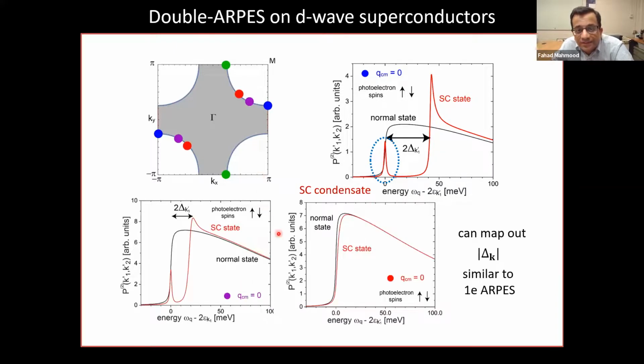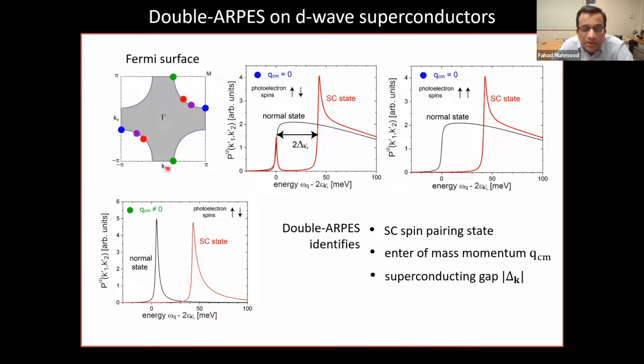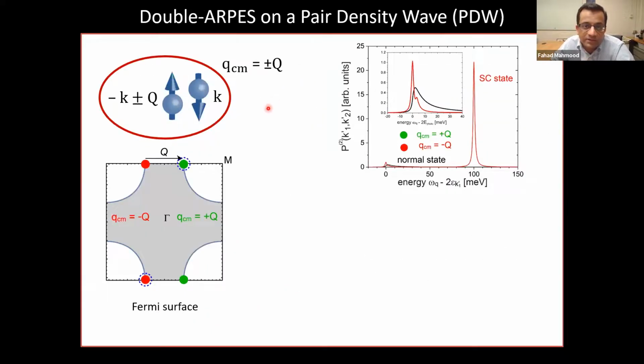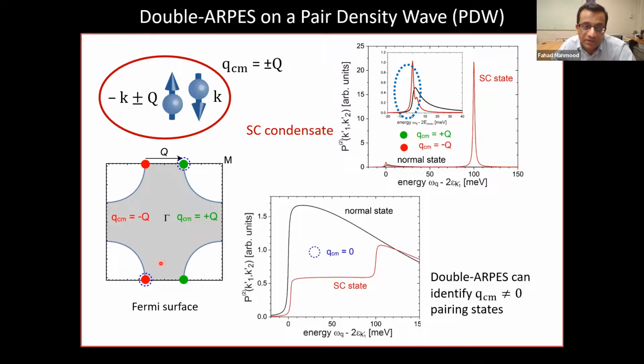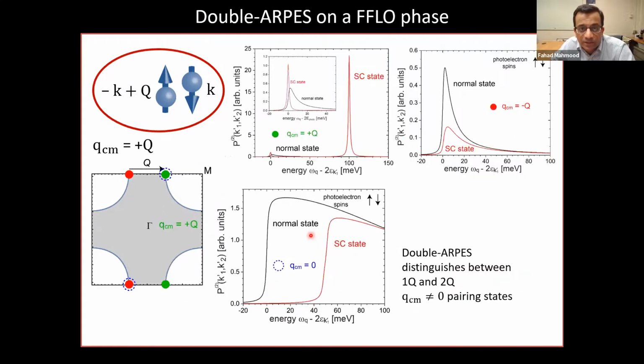If we do this at points that are not paired, for example, let me just go over here, these green points on a regular D-wave, then you do not see this zero frequency peak in the superconducting state. You only see this between points that are paired, okay? So taking this to, let's say, a pair density wave case, again, you only see the zero frequency peak if I'm probing points sort of opposite to them. So I'm probing points which are paired, but not points that are, let's say, effectively zero in the Cooper pair momentum. Okay, so I'm running out of time.